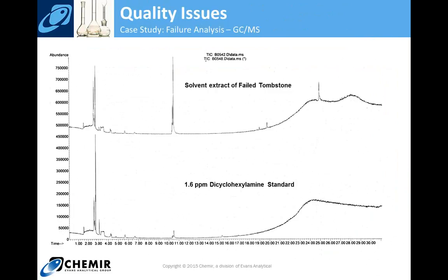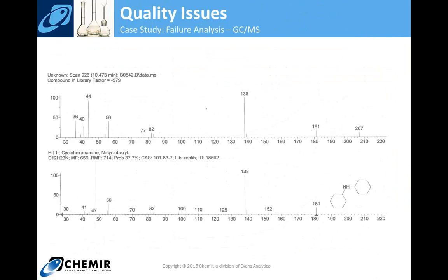Applying a different analytical technique, this is some data from gas chromatography analysis, where we extracted some of the failed regions of these tombstones using organic solvent. We would have done the same chemical extraction of control samples, of good materials, and compared them. What we're showing here is an extraction of the failed tombstone analyzed with GC mass spec, gas chromatography, showing evidence for dicyclohexylamine. So we have two different analytical techniques providing the same result: we're seeing dicyclohexylamine using IR and using a gas chromatography technique. So dicyclohexylamine is present. Here's a mass spectrum of dicyclohexylamine, just confirmation from the GC analysis. GC mass spec provides fragmentation of the organic molecule, which is another form of chemical fingerprint.